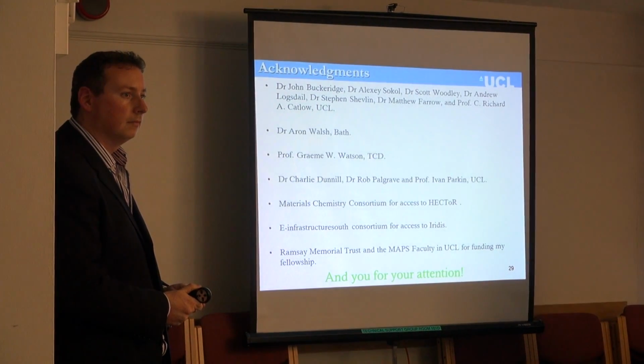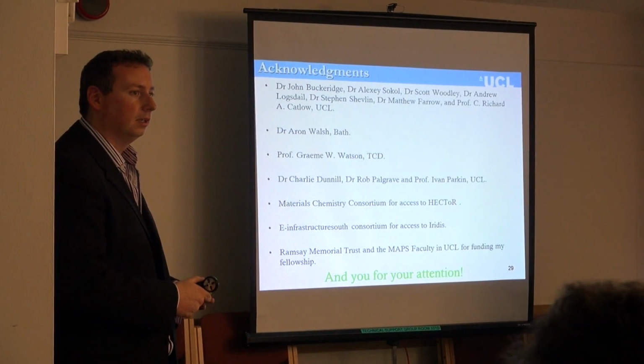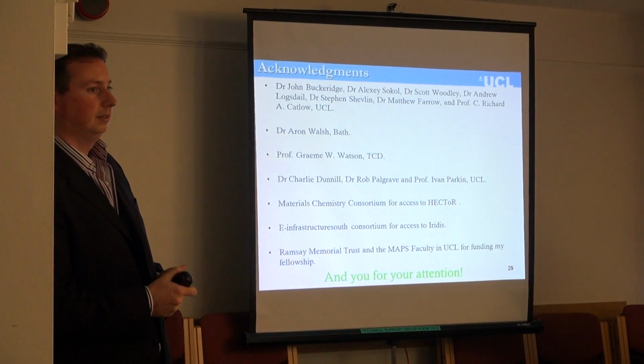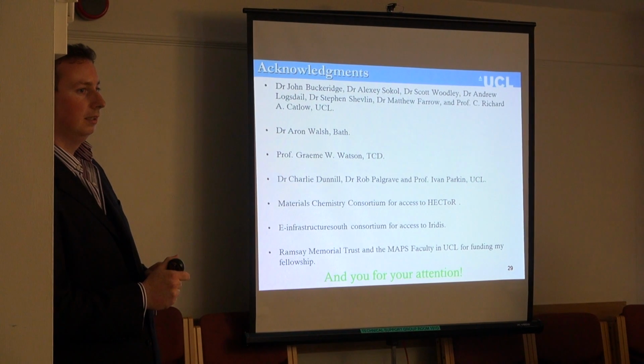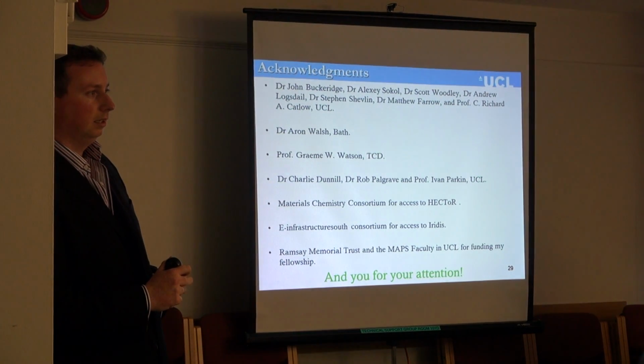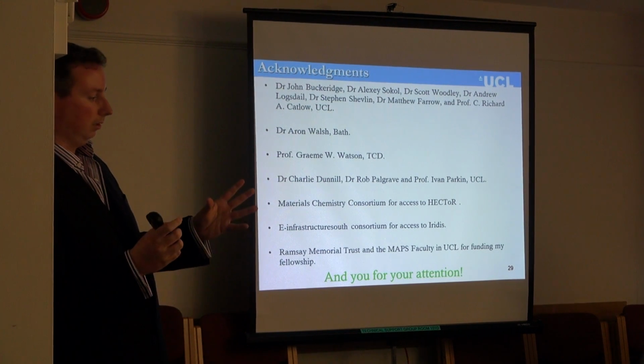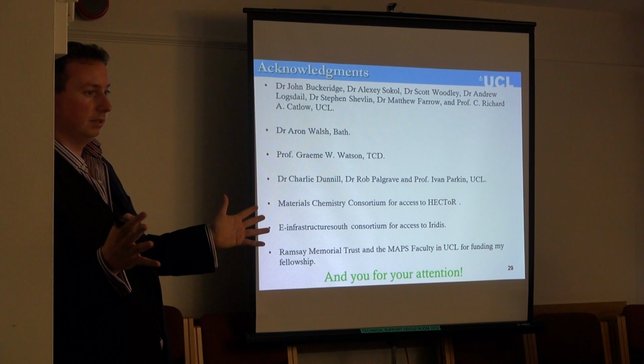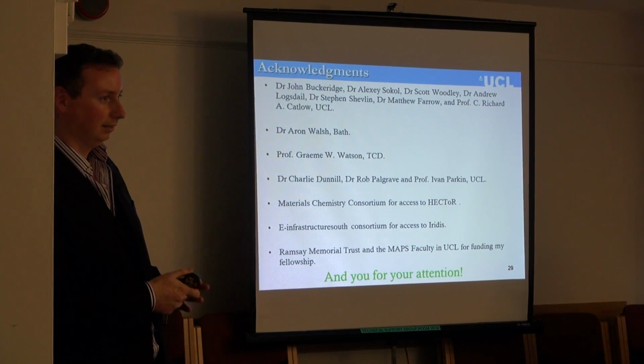Particle size effects: rutile and anatase exchange their thermodynamic stability in nano-sized particles. So is the size possibly playing any role in the results? No, because although we call it a cluster, it's an infinite model. So this is bulk.